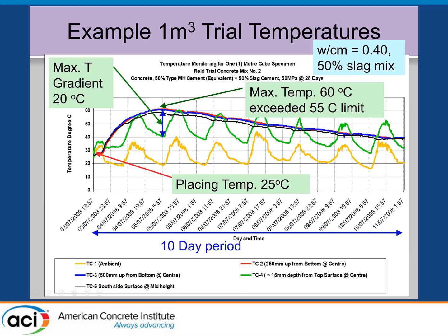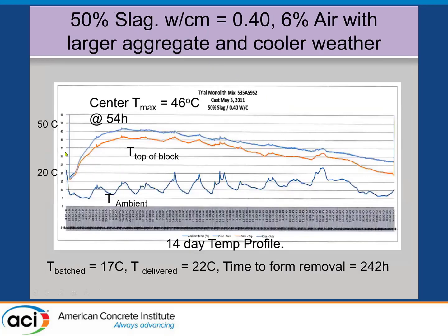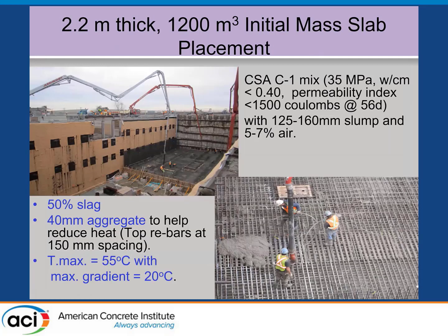Okay. And here's another one that we used larger aggregate and was cast in cooler weather, and we did meet the 55 degrees C in this case. And this shows over 14 days. We used this on one project with a big slab, a 2.2 meter thick slab, about 8 feet thick, large single placement, heavily reinforced, and we used large aggregate.